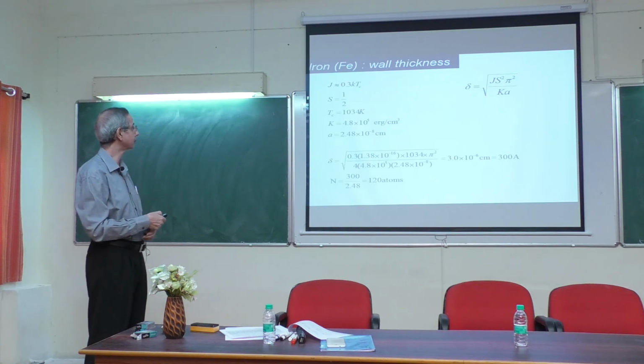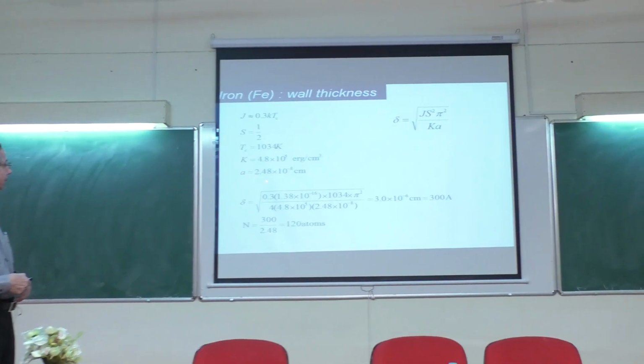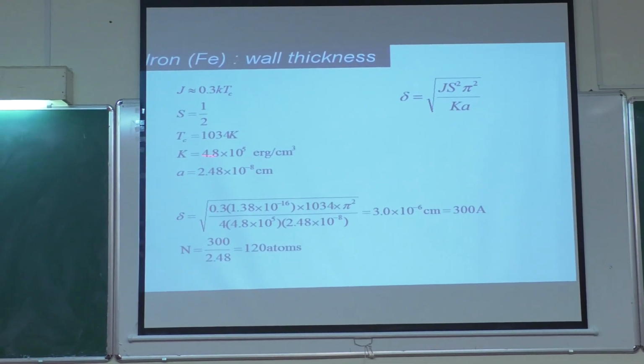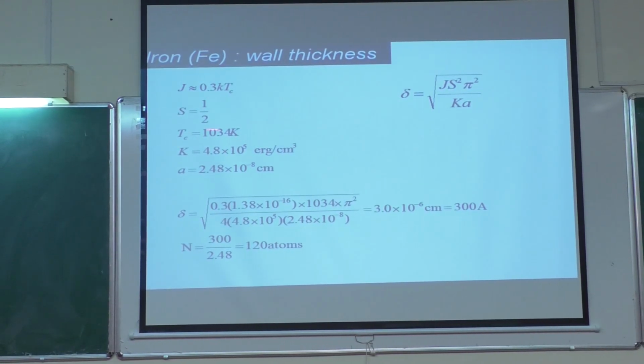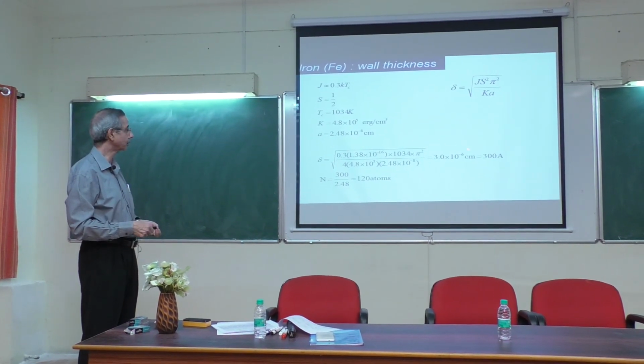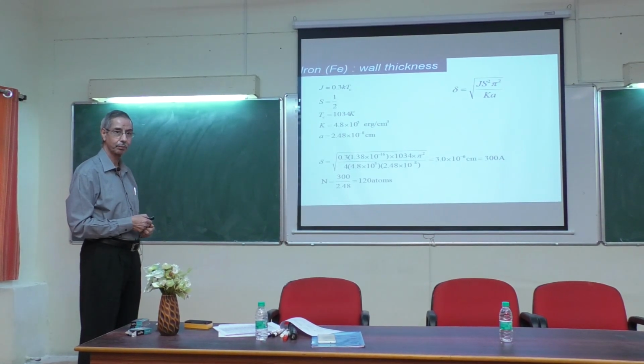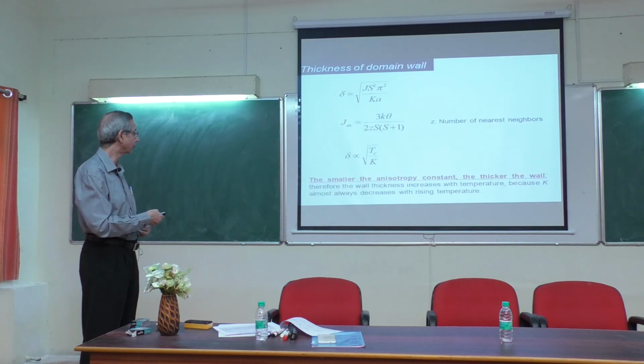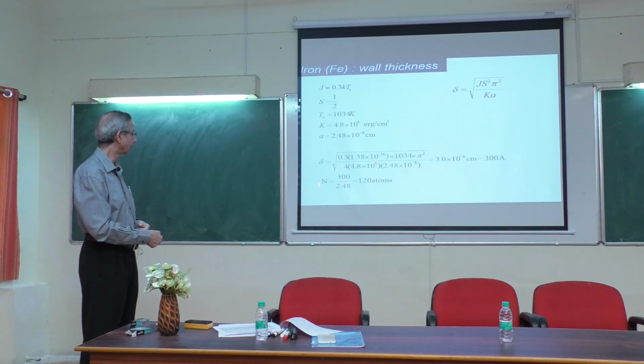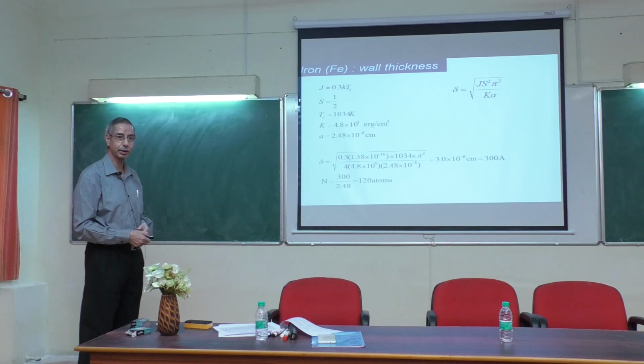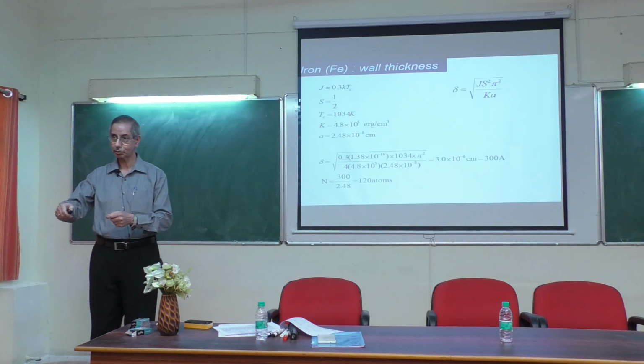Now just to give you an idea, let's say for iron, J is roughly this, and these are the lattice parameter, the value of K at room temperature, and this is the Tc value. If you plug in these values now, what you find is that the equilibrium domain wall width is of the order of 300 angstroms. And this corresponds to the number of atoms you are asking. So this corresponds to this divided by lattice parameter value. So that gives me about 120 atoms. So there are 120 atoms with spins within a domain wall. Understand?